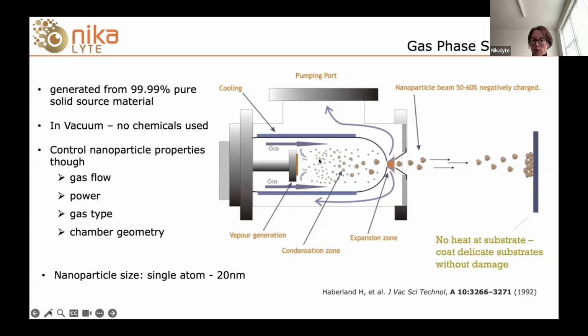Now, in magnetron sputtering, those atoms will effectively disperse and hit the substrate, and that will form your two-dimensional layer of material. In gas phase synthesis of nanoparticles, we have an additional process whereby those atoms of material are held in an additional chamber, which we call an aggregation zone. And it's in this aggregation zone that the nanoparticle properties are controlled. So we do this by changing the properties and the parameters in the system. There's various different parameters we can control.